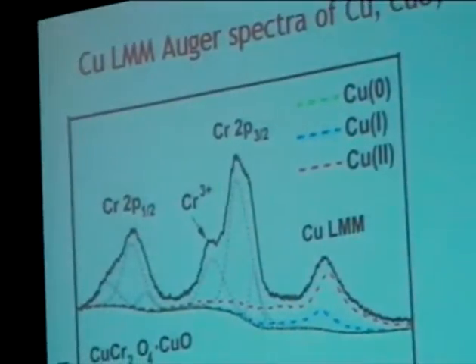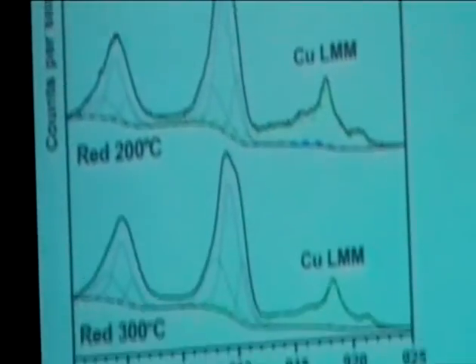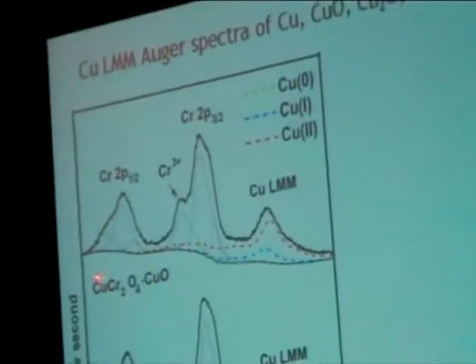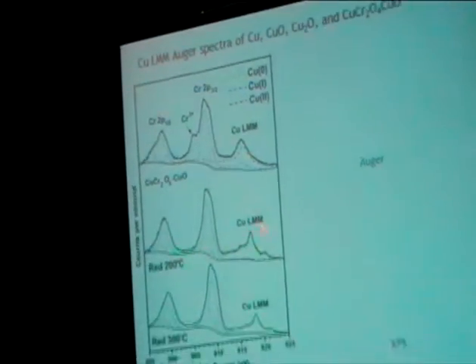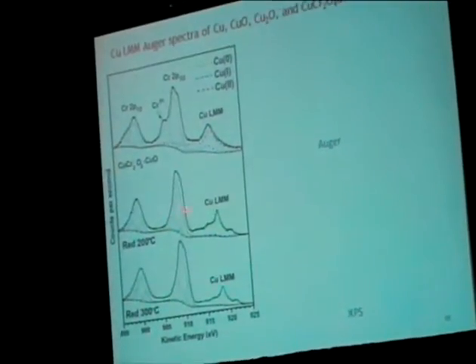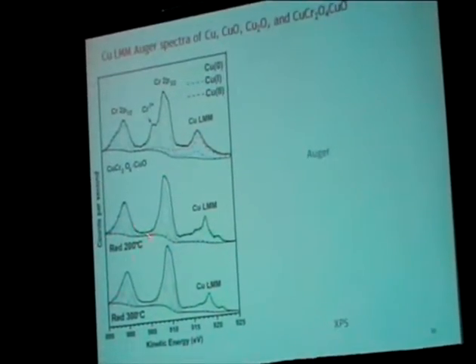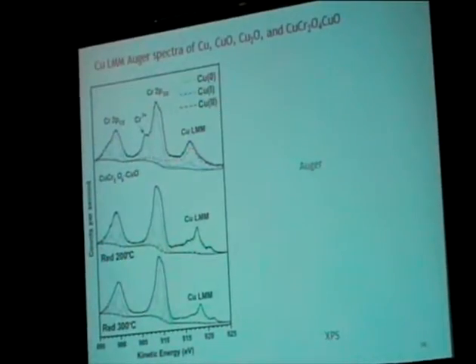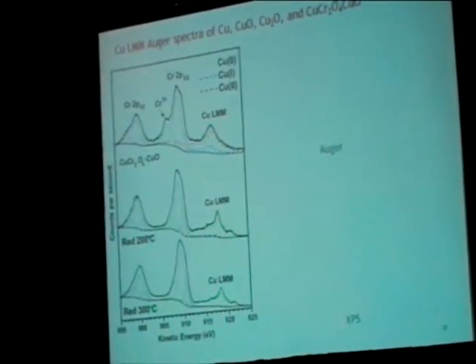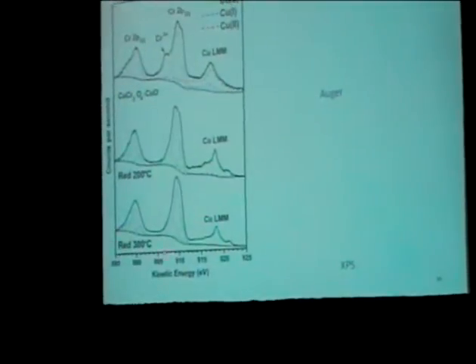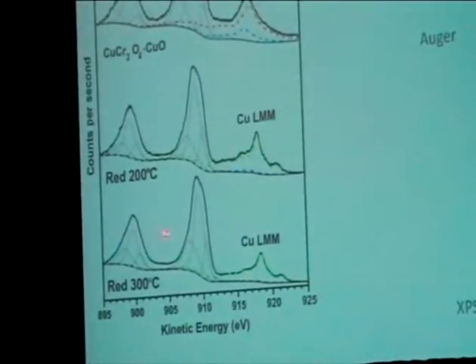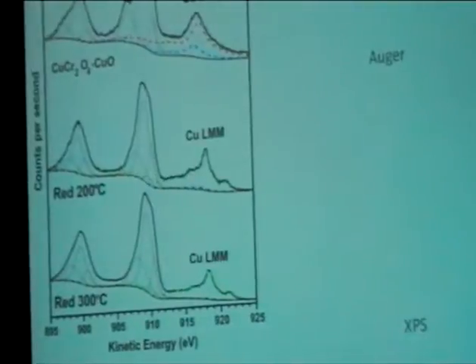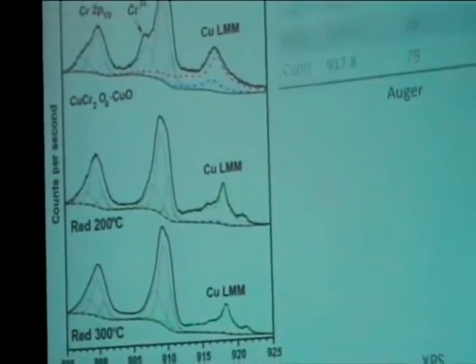Okay, we've also looked at the metals on here using Auger and XPS. Okay, and what you see first is here's the starting material, which is this copper oxide, chromium oxide type material. And what you see in this plot here is two different conditions. The material that's been reduced at 200 degrees, which I said is the most active catalyst, and the material that's been reduced at 300 degrees, in which we get a significant drop-off in the activity and selectivity of this catalyst.